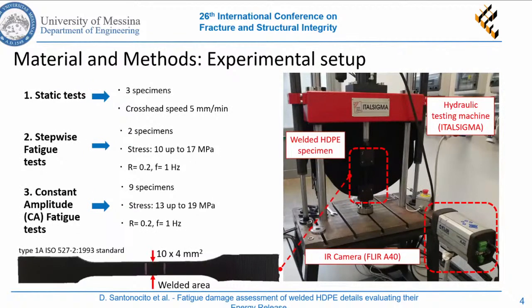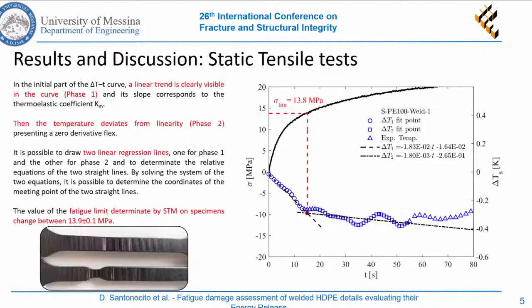We adopted, according to the ISO standard, welded high-density polyethylene specimens, and we performed 3 kinds of tests: static tensile test, stepwise fatigue test with an increasing applied stress level, and constant amplitude fatigue test, the traditional fatigue test. And we monitored the specimen surface temperature by means of an infrared camera.